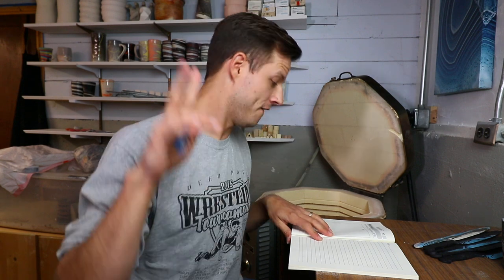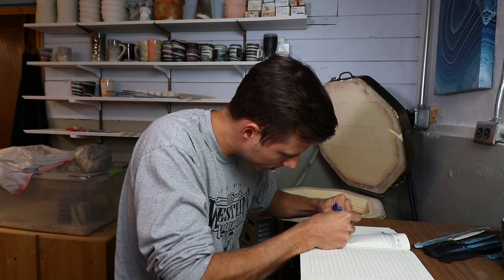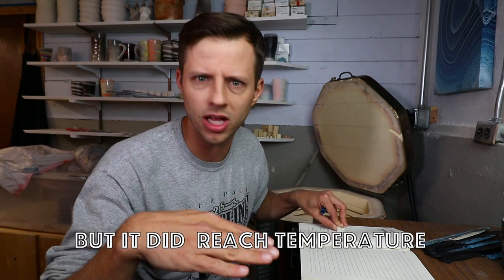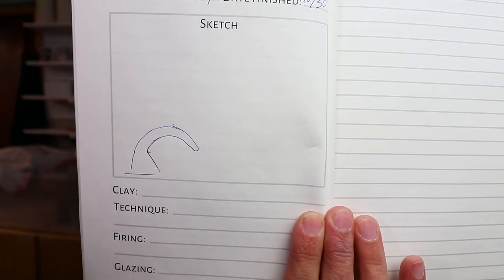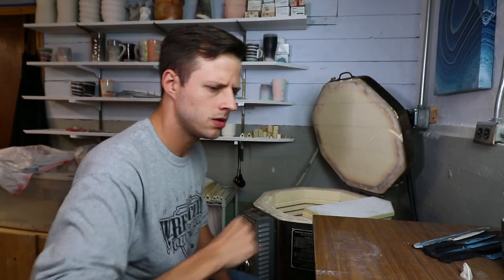I started this kiln on the 9th of October and finished it on the 30th. My last firing before this one that was a glaze turned out funky. As you've been following the channel, I figured out the whole kiln fiasco. It turned out that the wire that went back into the plug had also melted between my fixing it and my second firing. Having cones tipped off the fact that my kiln might not be working properly — and I was right. Only the top and middle element were working, and the work looked funky. There's the witness cone, and here's the witness cone from the shelf below — also pretty good, a little hotter than the shelf above.